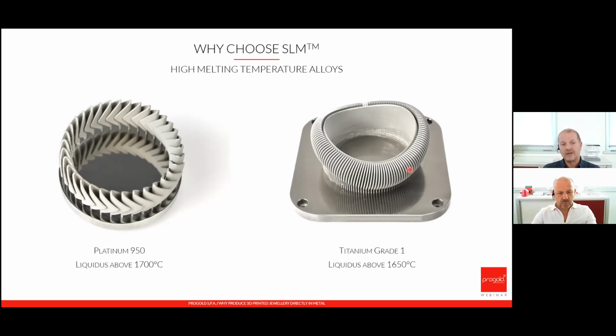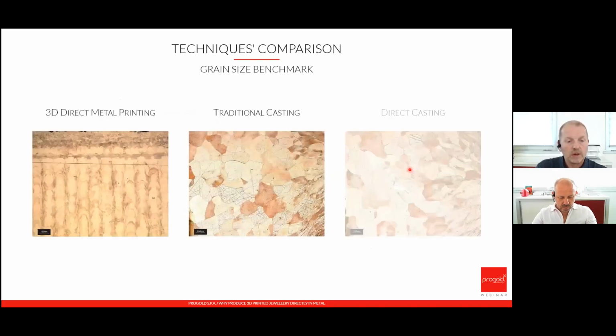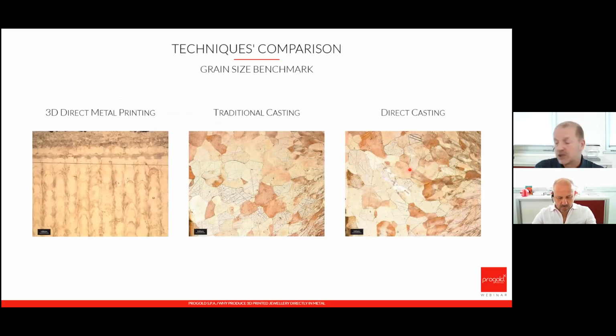And regarding titanium, you probably know that it's very difficult to cast material with a large number of scraps. Conversely, you get very impressive results with SLM with both these materials. This is just to remember that SLM is a melting process, and here we show a grain size benchmark among SLM, I would say metal direct 3D printing, traditional casting, and direct casting.